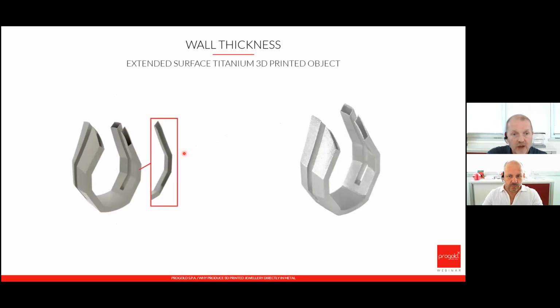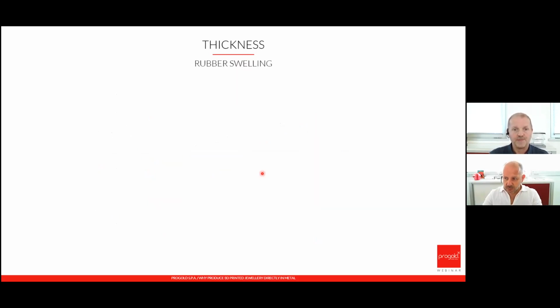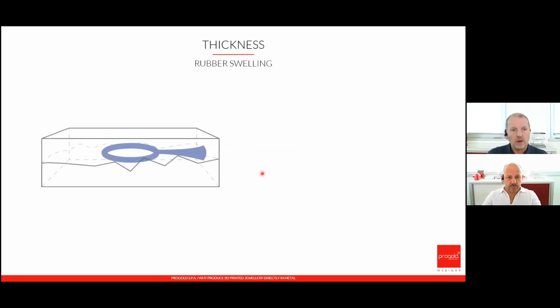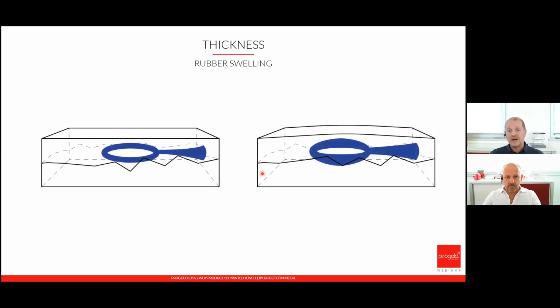This is an extended surface titanium 3D printed object, okay? On the left, just a virtual picture. On the right, the real picture of the part. We were able to produce this part with extended surfaces, maintaining a very low wall thickness. Okay. Regarding the thickness, you know that thin objects require higher injection pressure with the risk of rubber swelling.